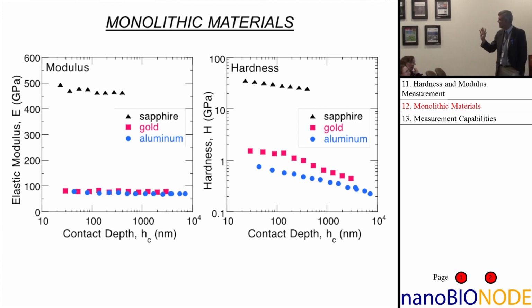which points to something that people have known for years, which is that hardness is not a good material parameter. In this case, you can see quite nicely that, if you believe those numbers, the hardness is increasing at small depths. That's something called the indentation size effect. When nanoindentation came in the late 80s, early 90s, people started seeing these things and asking what's causing that. There's a whole wealth of literature out there right now on the nature of that. And it gets back to something I implied a little earlier, which is that as you get smaller, the number of defects present in that material starts to change in a significant way and can change properties.